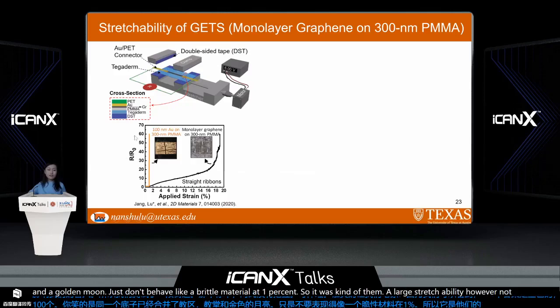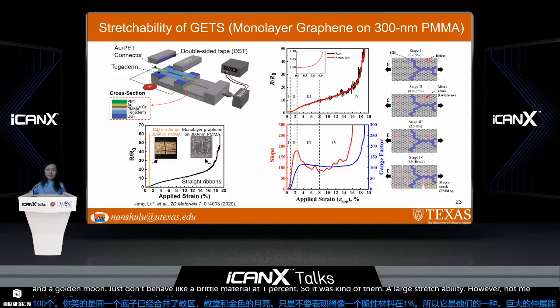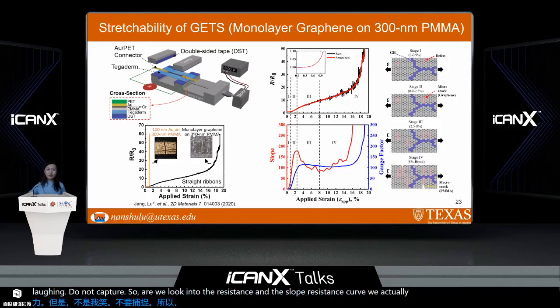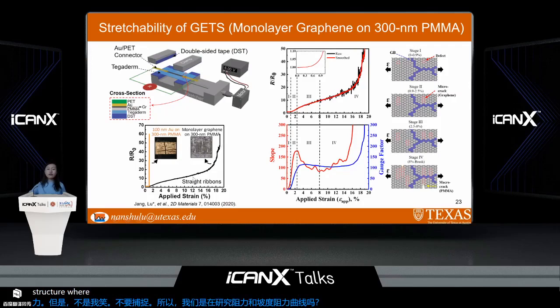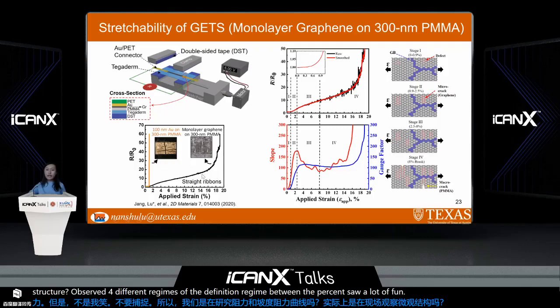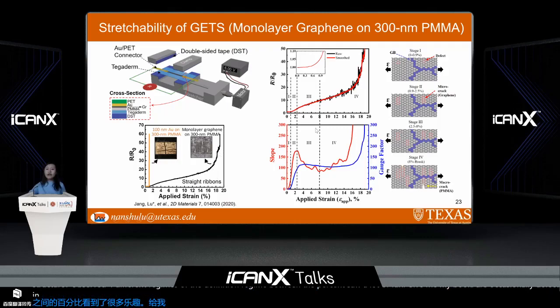So when we look into the resistance and the slope of the resistance curve, with in situ observation of the microstructure, we actually observed four different regimes of the deformation. In regime one, that is between 0 to 0.9%, we didn't see any microcrack. There are occasionally defects in the CVD graphene. But starting from 0.9%, we start to see very micro length cracks emerging in the monolayer graphene.